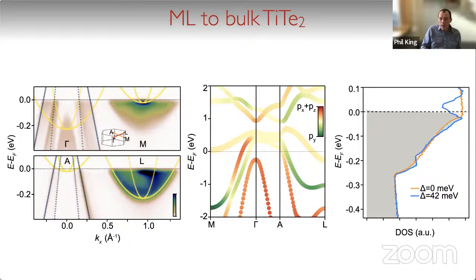And so we think ultimately that explains why the monolayer is susceptible to this charge density wave formation, while in the bulk, this electronic driving force for the charge density wave to occur is effectively completely removed by the three-dimensional band dispersions, including their out-of-plane band inversions that you have there.